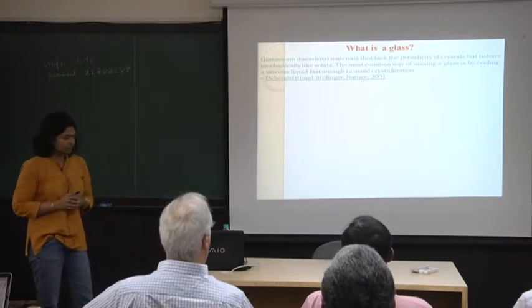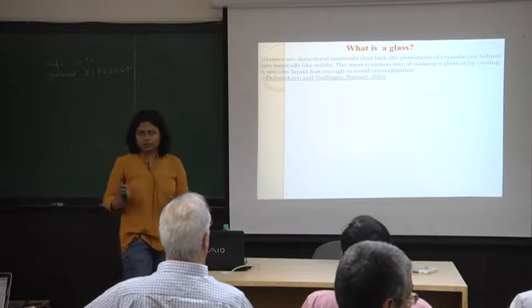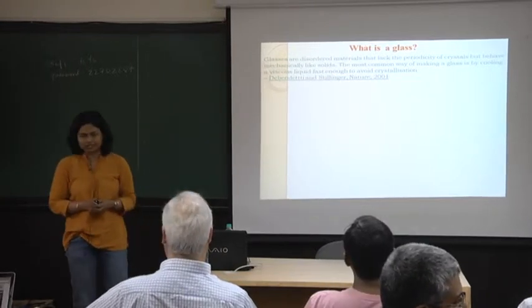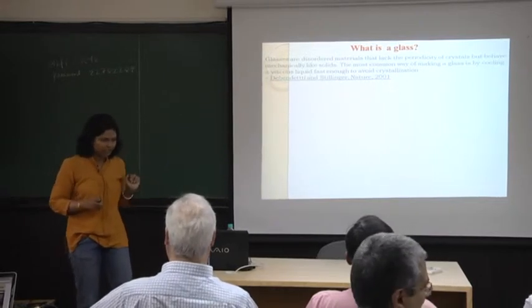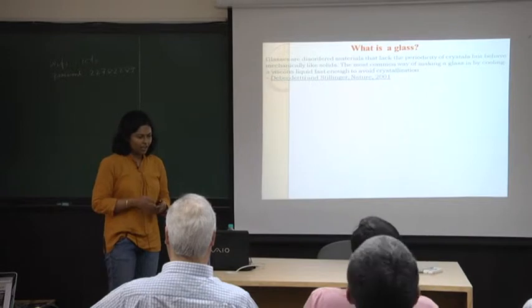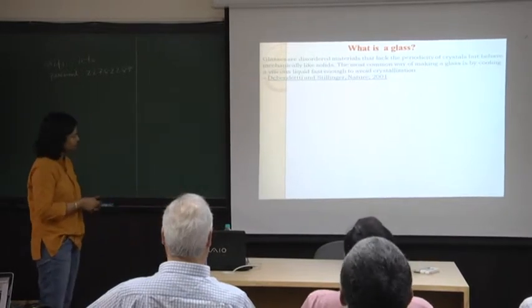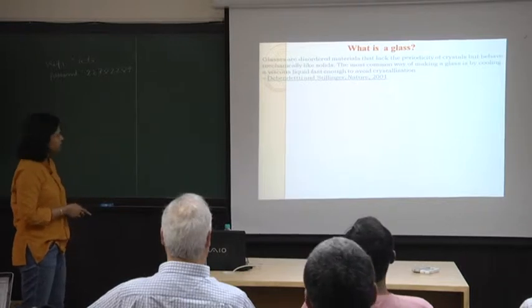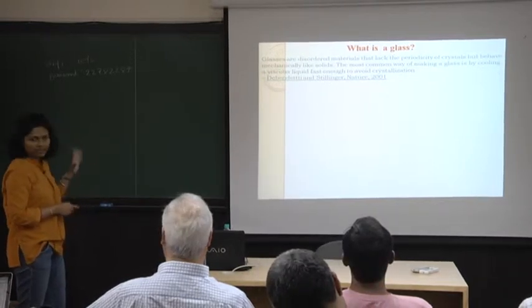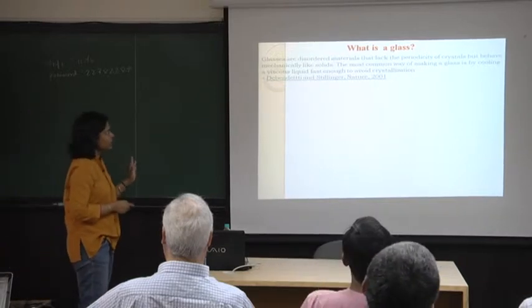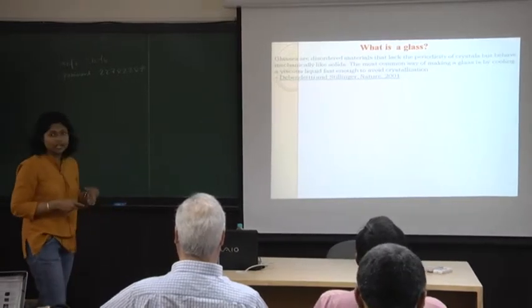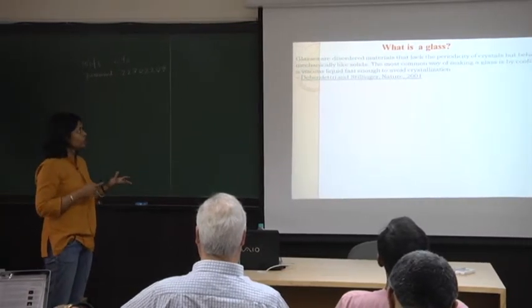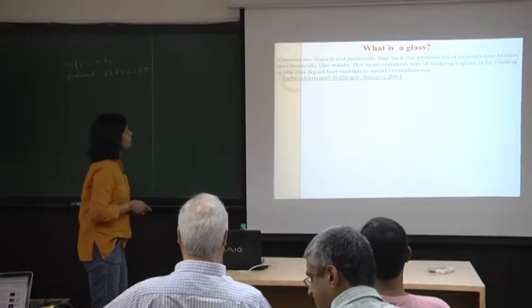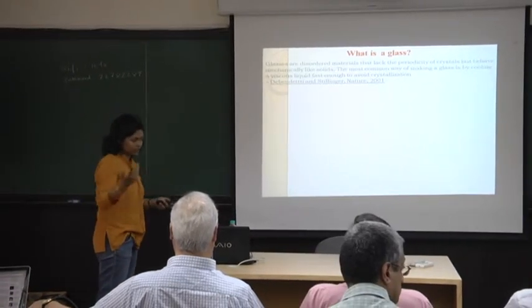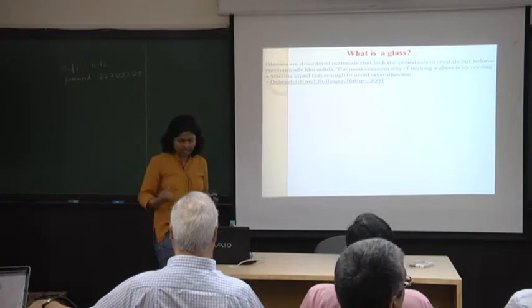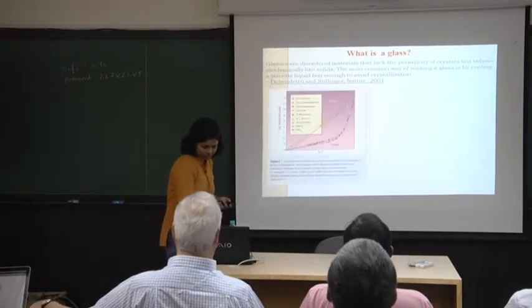Okay, so what is a glass? Now, because I work on colloidal glasses, I'm not going to use the IUPAC definition of glasses, which is that the viscosity rises by 13 decades in a few degrees of temperature. I'm going to use the first two lines of this ubiquitous and beautiful paper by Debenedetti and Stillinger in Nature, that we treat glasses as just disordered materials that do not have the periodicity of crystals. They are mechanically like solids, but if you could look at it structurally, it is really a liquid. Okay? In the case of the glasses that we were just hearing about, of course, you quench it really, really fast till the time the viscosity diverges.